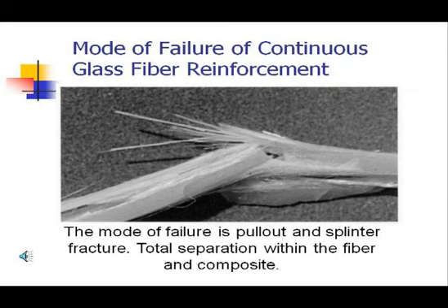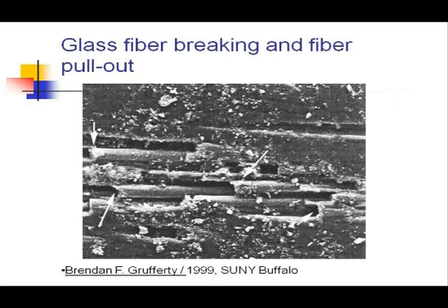So you have a high flexural strength, but when a flaw occurs within the composite, the crack starts and it continues all the way through. In fact, here you can see an SEM from a master's thesis of the pullout of the glass from the composite itself, so that the crack goes all the way through.